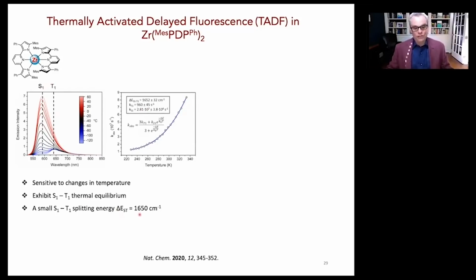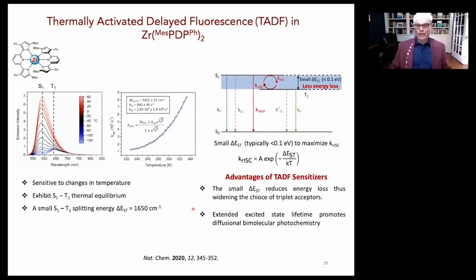But the idea really is that it's got a pretty small singlet triplet splitting. And this is the reason why the singlet manifold has this incredibly long lifetime. It's being fed back by this incredibly long lifetime ligand center triplet reservoir. So that sets you up in a really nice way for having very little Stokes loss. So the excited state you make is really retained. And then there's a number of groups worldwide that are using TADF photosensitizers in photochemical upconversion.